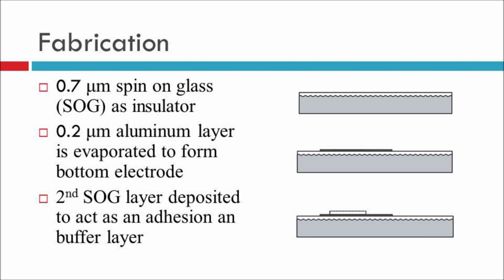The method of fabrication for this sensor is a fairly simple process. We start with applying a 0.7 micron spin-on glass layer as an insulator, which will prevent oxidation of the metal when we put on our zinc oxide piezoelectric element. Next, we evaporate a 0.2 micron aluminum layer to form the bottom electrode, after which we'll deposit a second spin-on glass layer that will act as an adhesion and buffer layer.